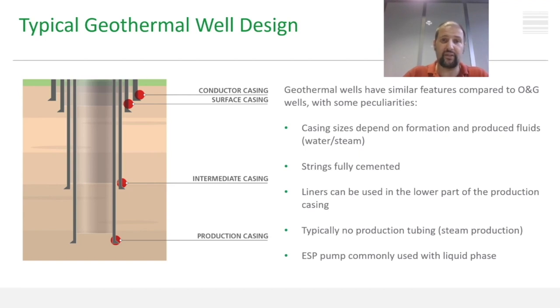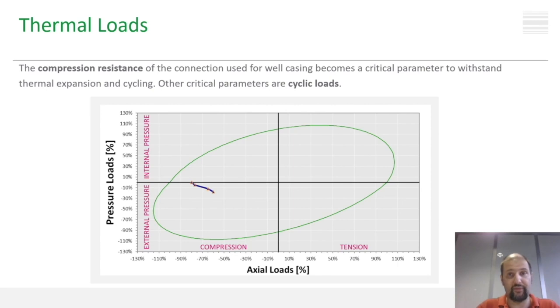In case of high enthalpy wells producing steam, typically the completion is tubingless, in order to maximize the passage area of the well. While on the low enthalpy ones, producing water, a shallow tubing connecting to an ESP pump is used. As we were mentioning before, geothermal wells are characterized by relevant thermal loads and cycles, especially during the production phase of their life. In this image, we represent a typical well load against the von Mises ellipse, where the x-axis is the actual load, tension and compression, while on the y-axis we can see the pressure loads, burst and collapse. The typical thermal loads involve compression and collapse load modes.